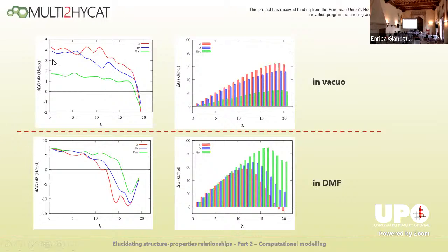And when we get these numbers, we integrate numerically this behavior, and this is the value of the delta G of adsorption that we get in the incremental value. You see that at the beginning it grows and then it gets lower. The contributions are negative at the end of the step. This means that at the beginning, when the molecule is strongly bound to the silica, there is a positive delta G when we decouple the system. But at the end, when the molecule is almost free, it is convenient for the system to free it completely. By the way, the different trends of these derivatives are automatically computed by the dynamics.